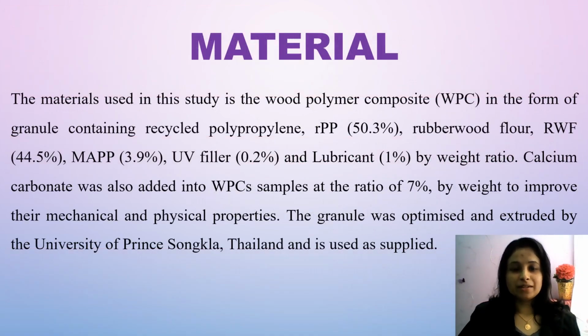Now, moving on to the materials. The material used in this study is the wood polymer composite, WPC, in the form of granules containing recycled polypropylene about 50.3%, rubber wood flour about 44.5%, MAPP about 3.9%, UV filler about 0.2%, and lubricant about 1% by weight ratio. Calcium carbonate was also added into the WPC sample at the ratio of 7% by weight to improve their mechanical and physical properties. The granules were optimized and extruded by the Prince of Songkla University, Thailand, and are used as supplied.